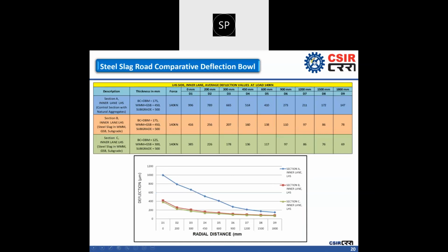In this particular graph, you can see the comparative deflection bowl of the steel slag road from D1 to D9 sensor in the inner lane. In the inner lane, the highest deflection is around 1,000 micrometer, and then this deflection gets reduced to between 375 to 400 micrometer. So it is almost a 60 to 70% reduction in surface deflection, which is primarily the cause of fatigue and rutting strain in the pavement. By virtue of that, the design life of this particular road, which has been found through the back calculation method after heavyweight deflectometer evaluation, is between 60 to 80 years in comparison to 20 years as prescribed in IRC 37. So it's a highly durable road which has been constructed using 100% processed steel slag aggregate in comparison to natural aggregate.